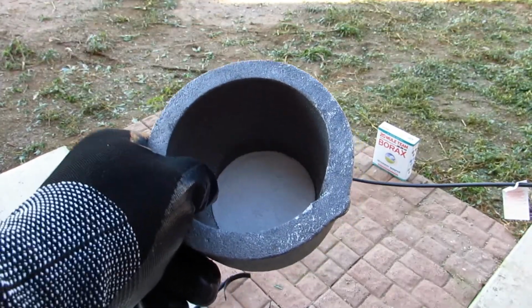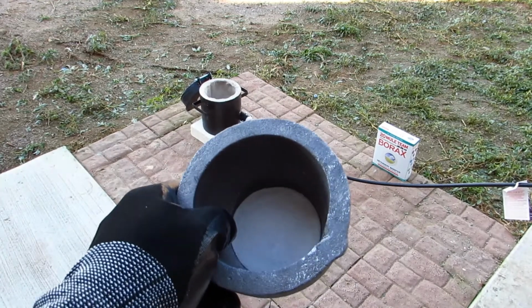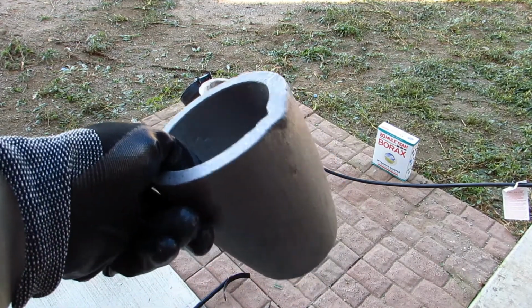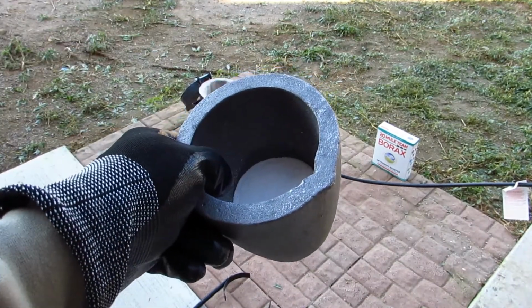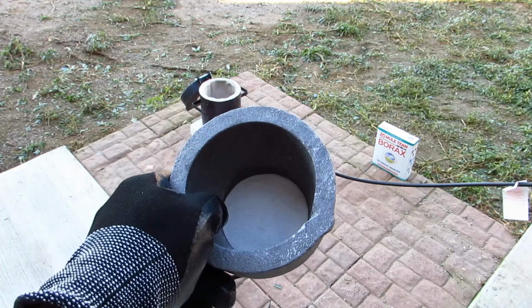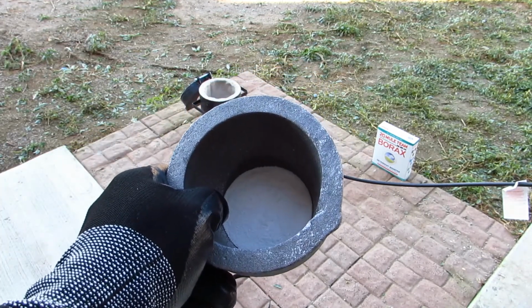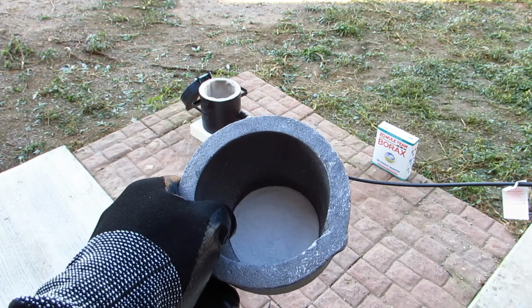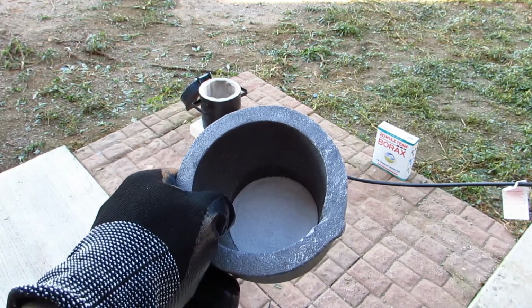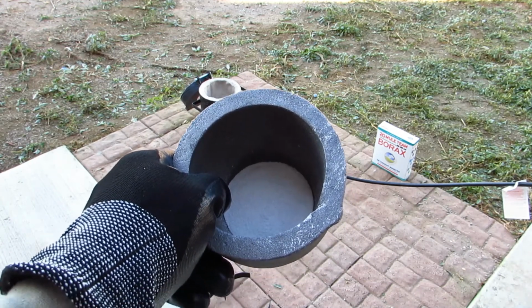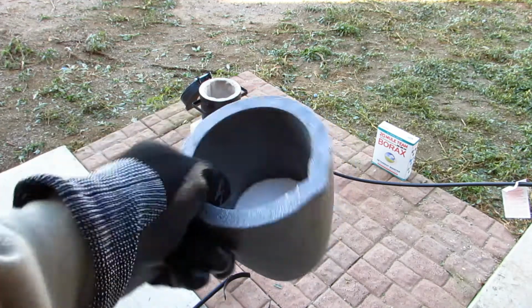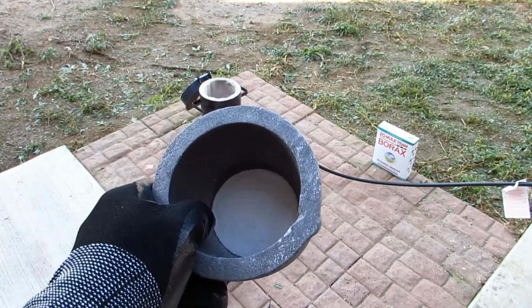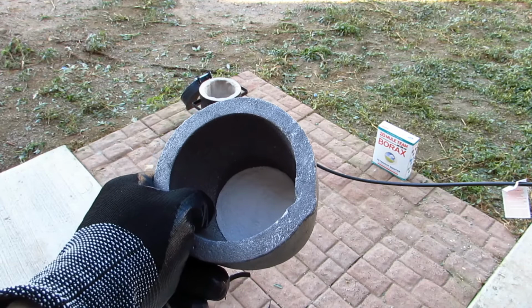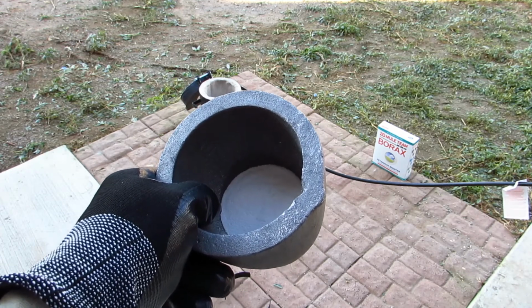I've not really come up with an exact science for how much borax to put in the crucible. This is a number 3 clay graphite crucible. I usually fill it up to about maybe 1/4 of the way to the top, and then melt it in the furnace. Once the borax is liquid, you use the tongs and swish it around a little bit to coat the inside of the crucible, and then pour the excess out.